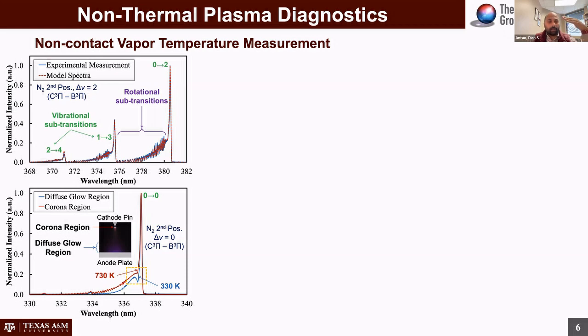electrode and you put it close to that powered electrode, you tend to develop what you call a very low excitation region, a diffuse glow region near this unpowered electrode. And based on our measurements of temperature near this diffuse glow region, we see that the temperatures are close to room temperature, about 50 to 60 degrees centigrade at the most.